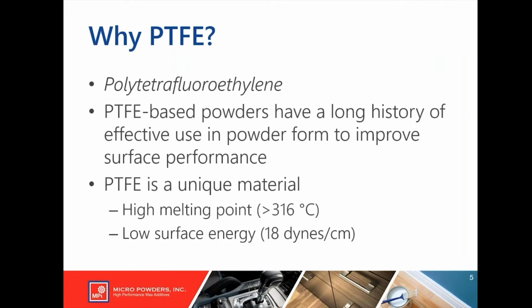So why are we talking about PTFE today? PTFE, in case you don't know, is polytetrafluoroethylene. And PTFE powders have decades of history in the coatings area as an additive to improve surface performance. And why is it such an important material for many decades? Well, PTFE is a very unique material. Firstly, a very high melting point, over 316C. That's very high. Typically, you never reach those temperatures in any kind of coating operation. And secondly, also very important is the very low surface energy of PTFE, 18 dynes per centimeter. High melting and very slippery material.